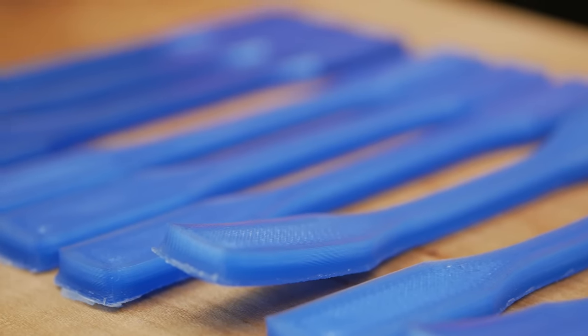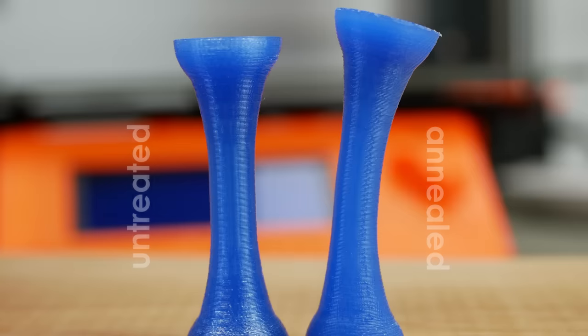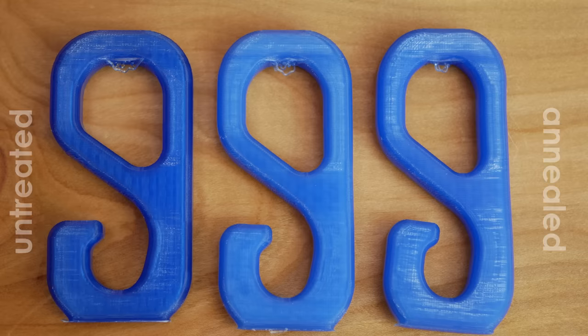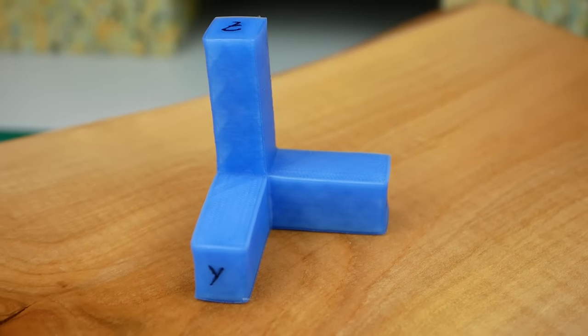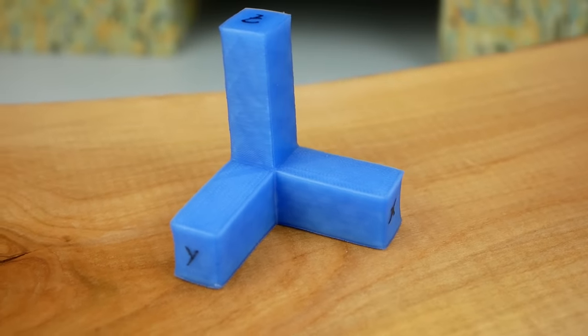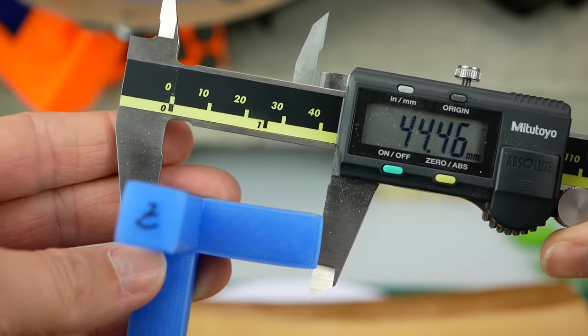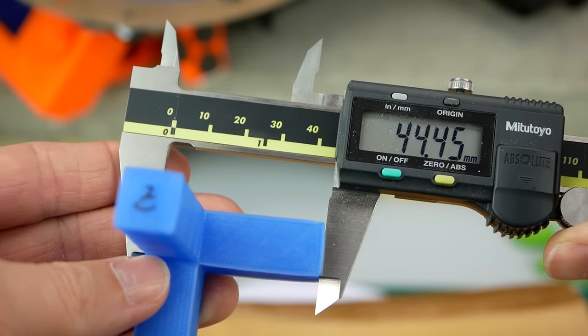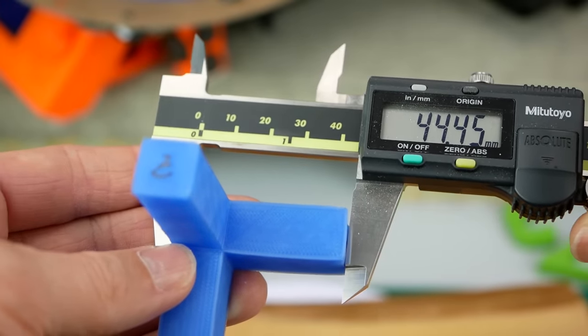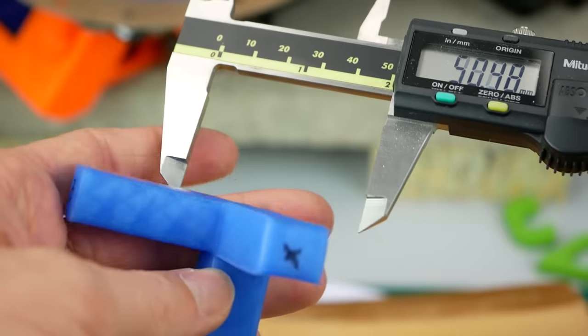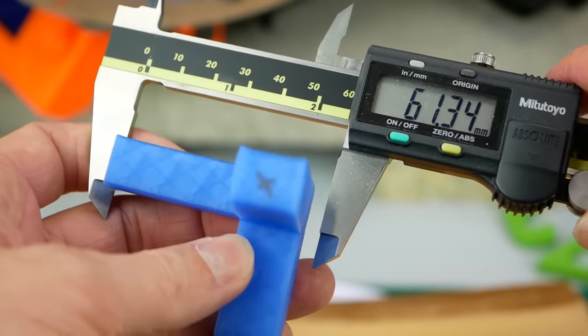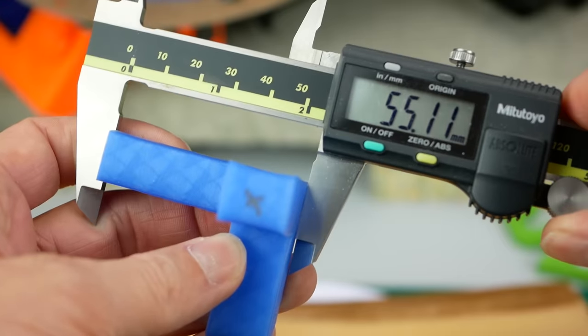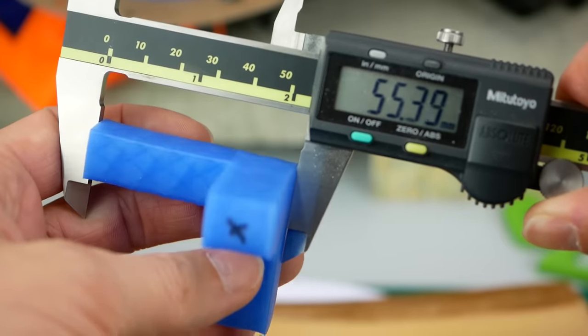Most obviously, some of the parts were really deformed and, for example, my layer adhesion samples were totally bent. Fortunately though, the standing test hooks still looked usable. I measured a couple of parts and the dimensional change was up to 10%. The interesting thing is that the parts contracted in X direction, so a 50mm part came out only measuring 45mm but they expanded in Z direction, for example from 50mm initially to 55mm after the process.